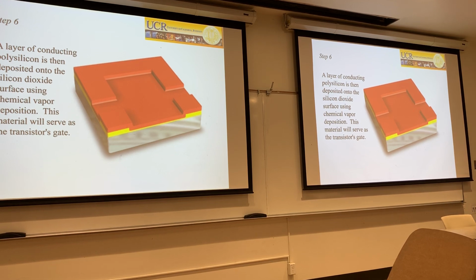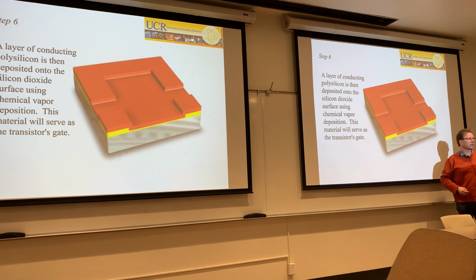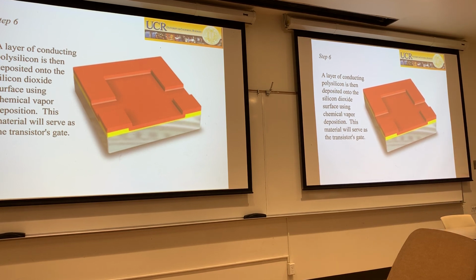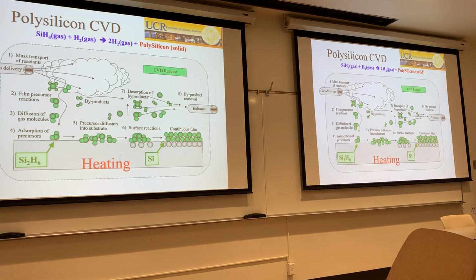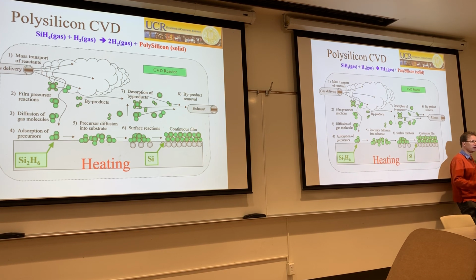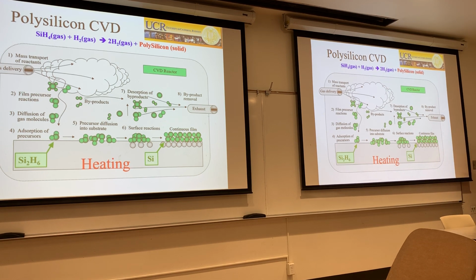silicon, and they deposit silicon in an amorphous way here. Not making a nice crystal of silicon, but making a jumble of atoms of silicon there. And if you have a jumble of silicon atoms, which you call polycrystalline silicon or polysilicon for short, then it becomes really very metallic. So this is actually metal now. And the way to do that is chemical vapor deposition, CVD, which is a process where in the gas phase, often at reduced pressure, you start out from reacting species. In the case of silicon, it might be silane, the methane analog to silicon. One silicon atom with 4 hydrogen atoms in the gas phase. You expose your substrate to that, you heat the substrate, and on the heated substrate, the silane will